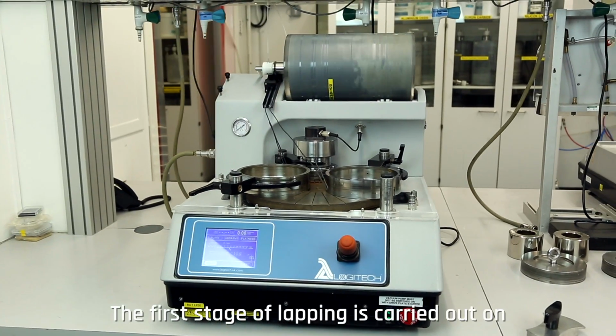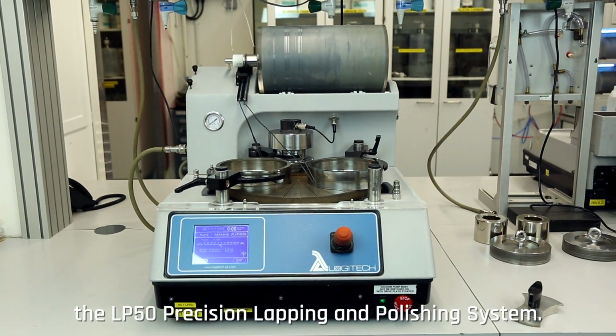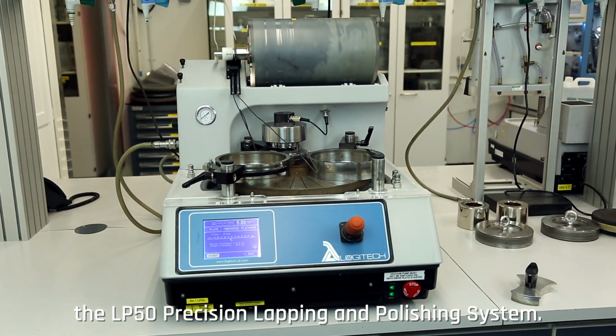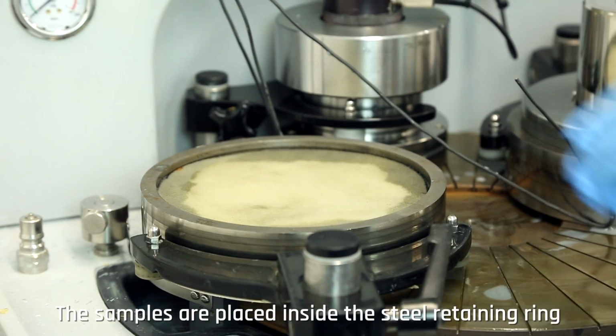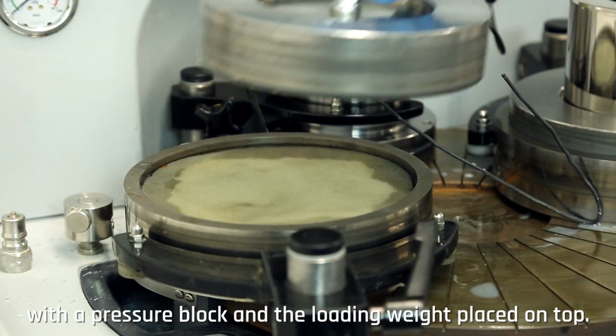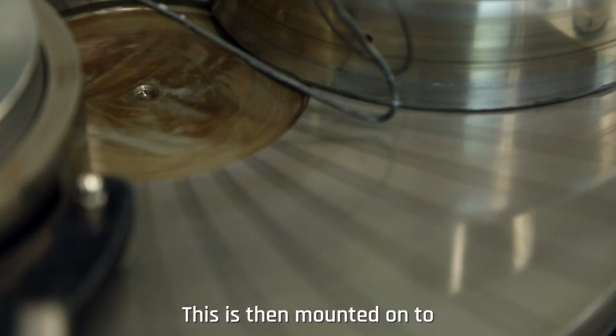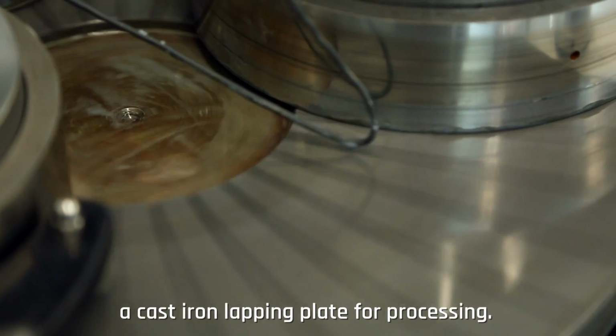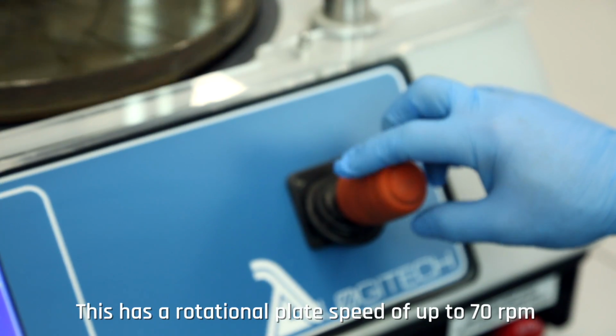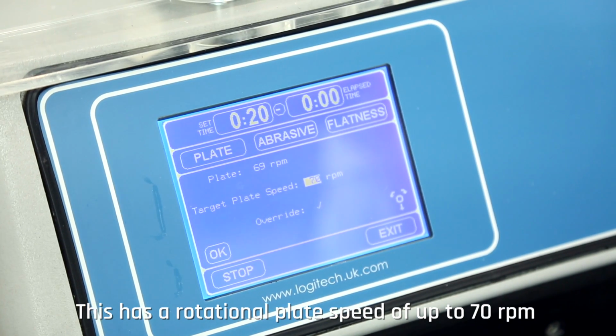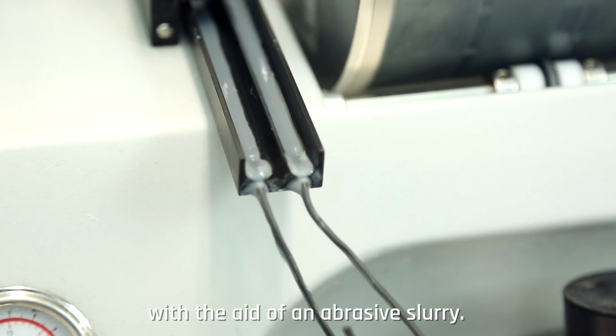The first stage of lapping is carried out on the LP50 precision lapping and polishing system. The samples are placed inside the steel retaining ring with a pressure block and loading weight placed on top. This is then mounted onto a cast iron lapping plate for processing. This has a rotational plate speed of up to 70 RPM with the aid of an abrasive slurry.